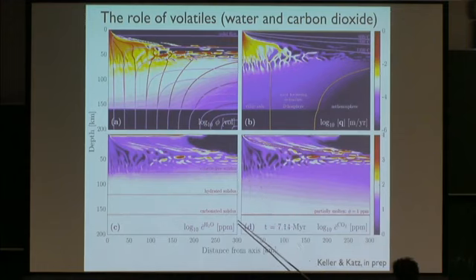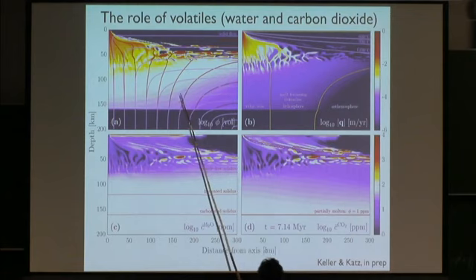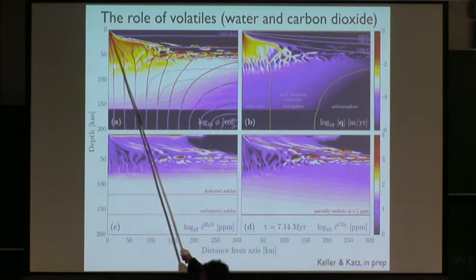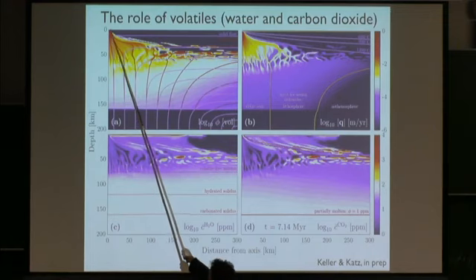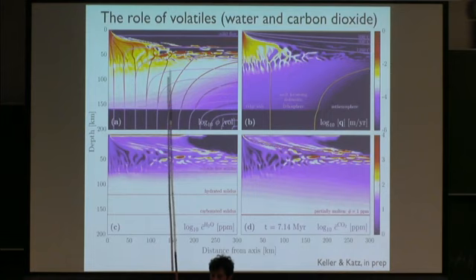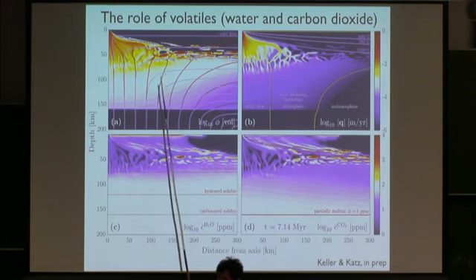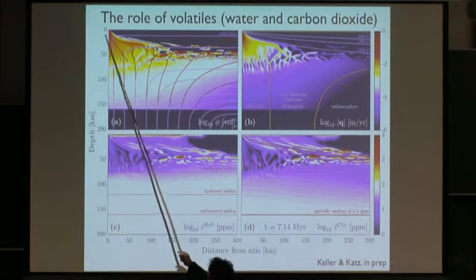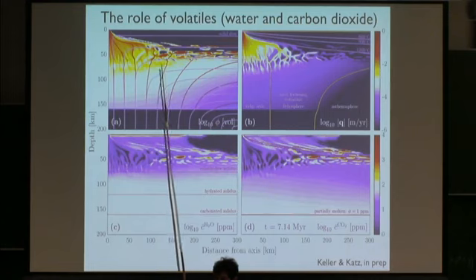And what's your maximum porosity near the ridge? Do you have a porosity scale? These things probably go up to a few percent near the ridge. So we've got a slightly different boundary condition here. It's a few grid cells over which melt is allowed to leave through the top of the domain because it is prevented from freezing. So in this disequilibrium formulation, we can just say turn the freezing rate off.